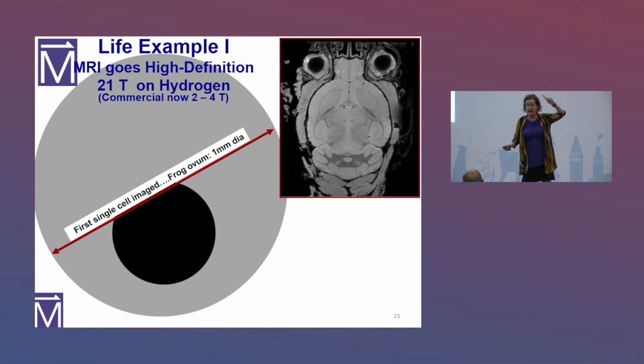So here's one example. How many people have been in an MRI? Probably anyone over about 25 has. The best thing about an MRI is you get to go inside of a superconducting magnet, right? That's very cool. But the MRIs that you get in the hospital are 3 and 5 Tesla. There's a lot of reasons for that. Another reason is that you don't really want to go too much higher, because if you increase the magnetic field, you have to increase the RF field in which you're measuring. You have a resonance condition between the field and the RF field in which you do the magnetic resonance imaging. So typically you can see about a 1 millimeter resolution.